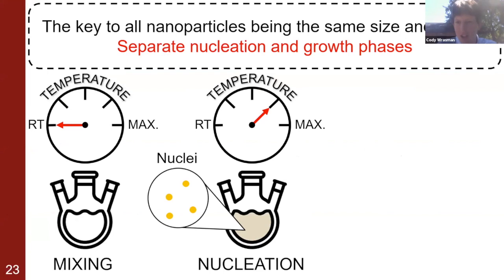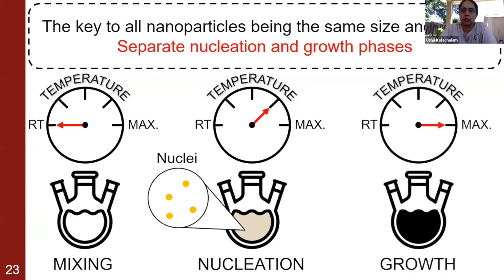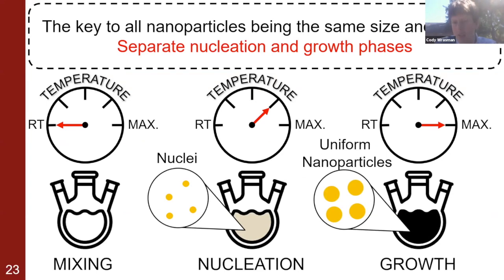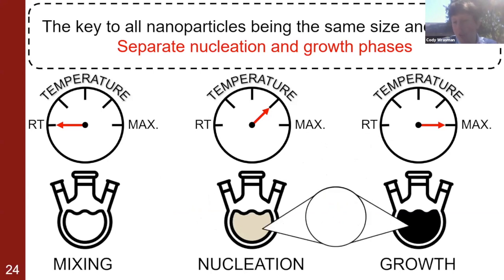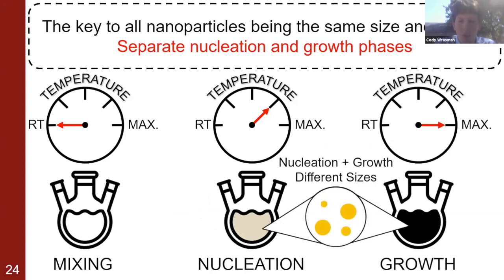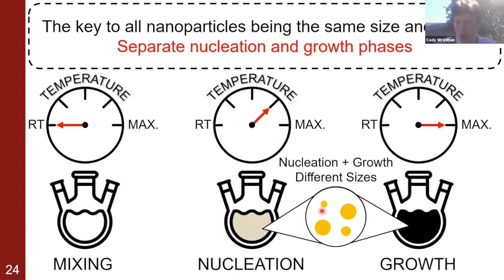I think I was just trying to explain that separating the nucleation and growth steps is important for making uniform nanoparticles. If you're able to separate that, in one step you'd have these nuclei, and then as you continue to increase the temperature, those nuclei would grow and form these very uniform nanoparticles. The difficulty being that if you have both nucleation and growth at the same time, you end up with nanoparticles with a lot of different sizes, where you have some very small nuclei that are just getting started, and other nanoparticles that have been growing for a lot longer time. So you'd end up with some small particles and large particles. Now, as I mentioned, that might make properties difficult to determine in the future.